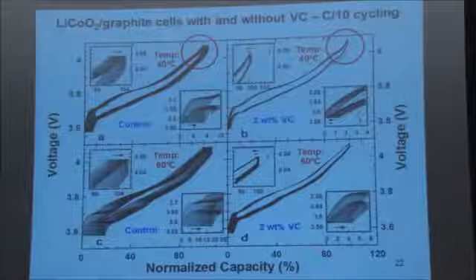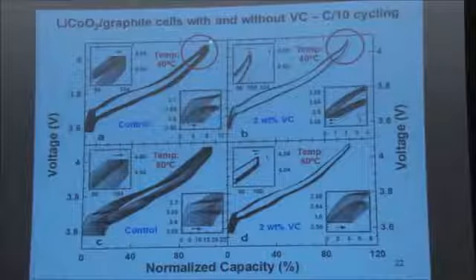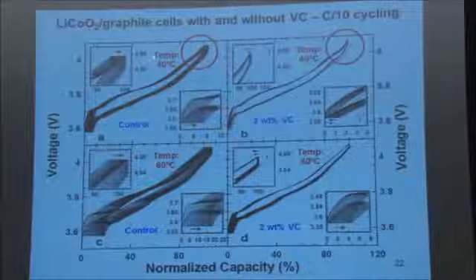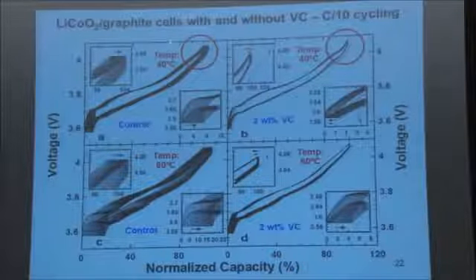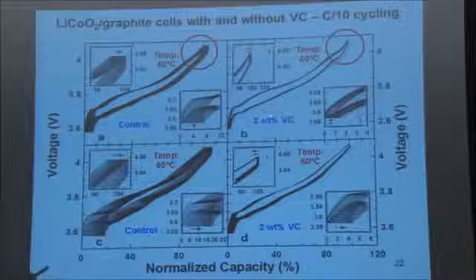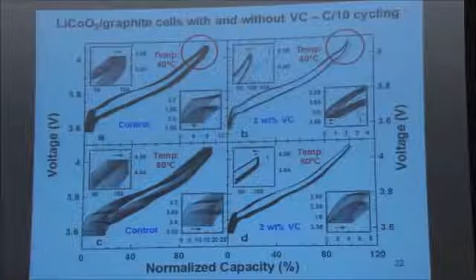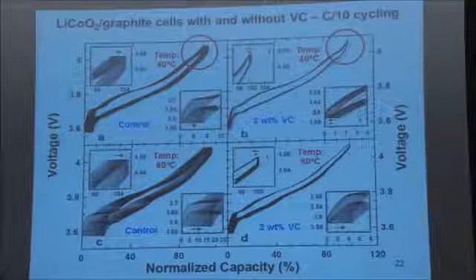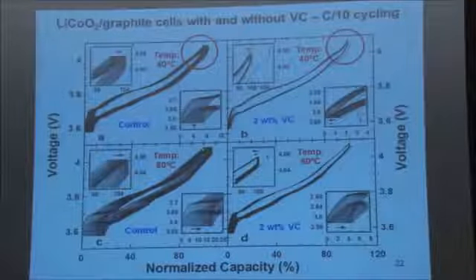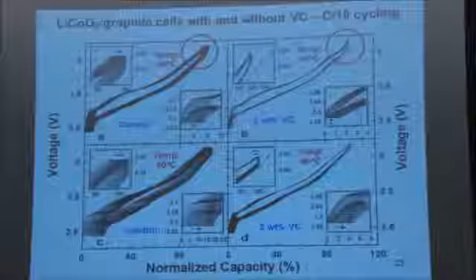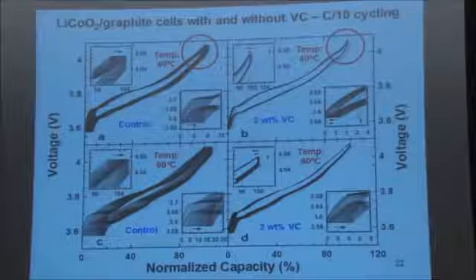So here, I'll just show you the impact of vinylene carbonate. So here are lithium cobalt oxide graphite lithium-ion cells. They're being cycled with the high precision charging equipment. So as you charge and discharge, you can see the voltage capacity curve, again, shifting to the right. And this is caused by parasitic reactions taking place, causing electrolyte oxidation at the positive electrode. The thing is slipping to the right. So the cell measured at 40 degrees C. But if you add vinylene carbonate to the electrolyte, bang, just stops. Okay, so you really impact that parasitic reaction a lot with 2% by weight of an electrolyte additive. And the same thing happens at 60 degrees C. There's a huge improvement in the rate of electrolyte oxidation at the positive electrode side.